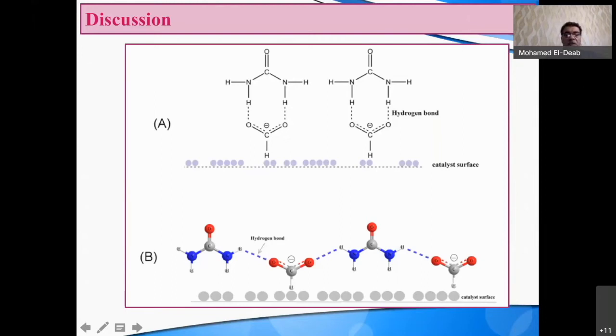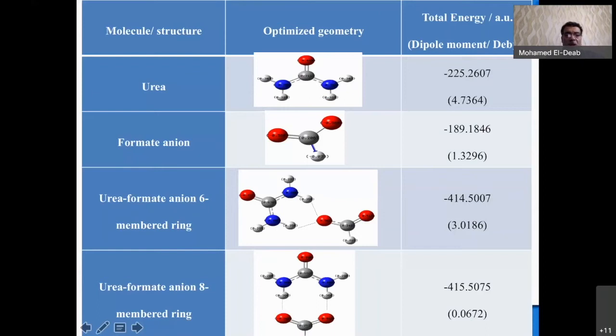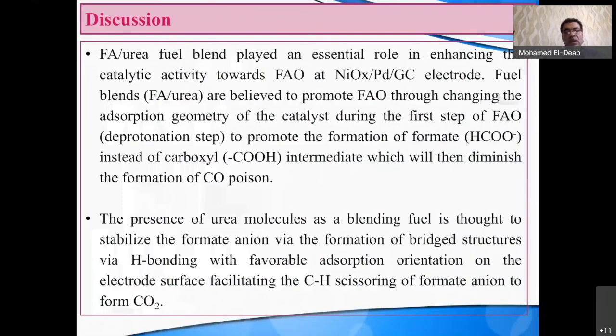Another proposal, we propose a linear polymeric chain, as you can see here. This linear polymeric chain also orients the formate anion CH bond towards the catalyst layer, so it is easy to cut. And this is supported by some DFT calculations in which we found that the presence of urea stabilizes the formate anion, and also it increases the dipole moment, which means that we can have some proper adsorption of formate anion atop the catalyst layer. So we propose this one, and this paper has been published in Renewable Energy Journal this year. And this is a discussion of the obtained results.